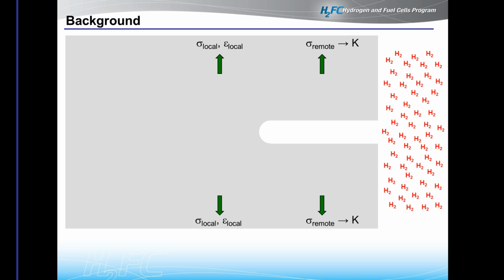So if hydrogen is present, that doesn't necessarily indicate that we will have hydrogen embrittlement. There are many steps that actually need to occur in order for hydrogen to get to the site where it can cause embrittlement, and those are often overlooked, and we just assume if there's hydrogen, then there's hydrogen embrittlement. But really what has to happen is multiple steps.